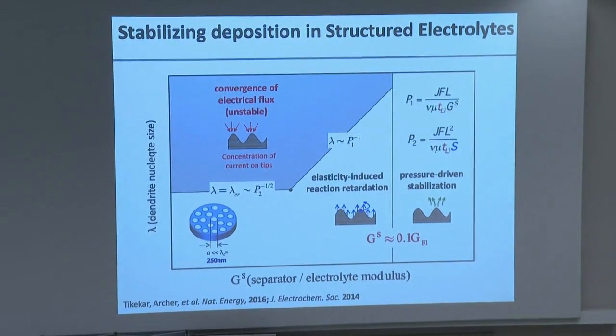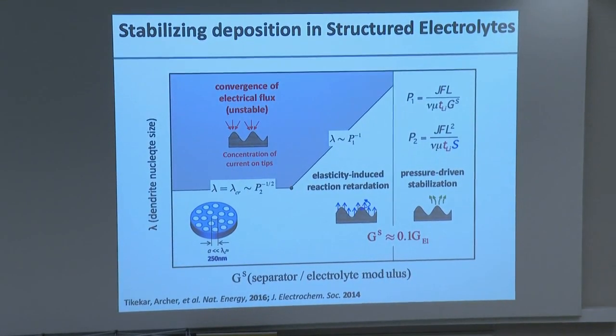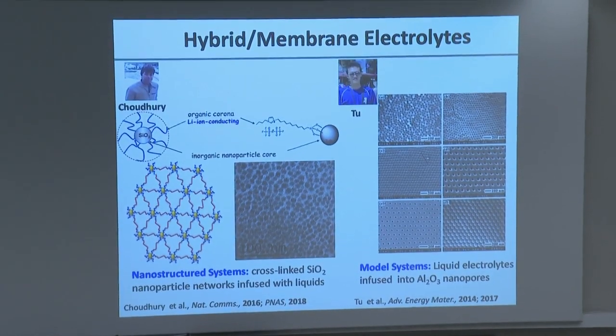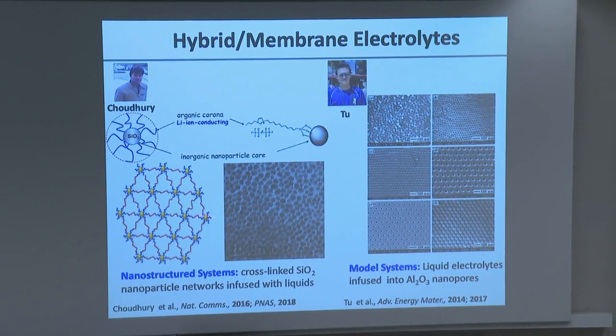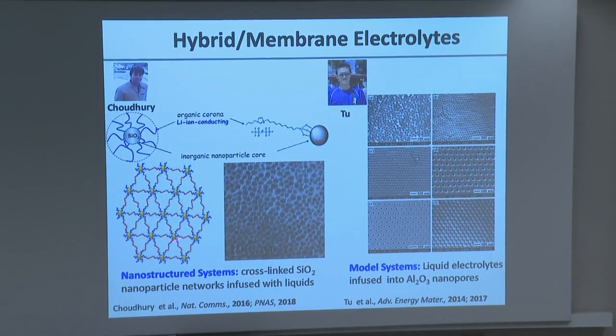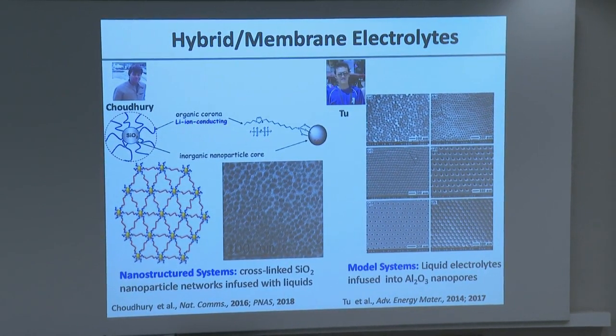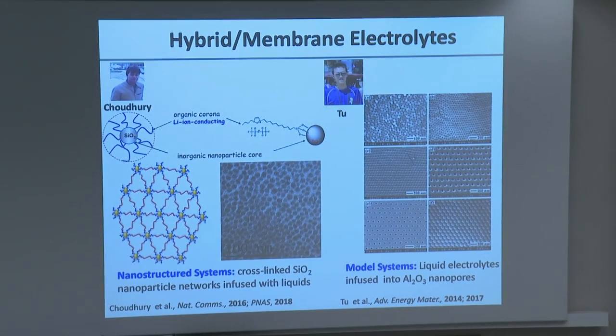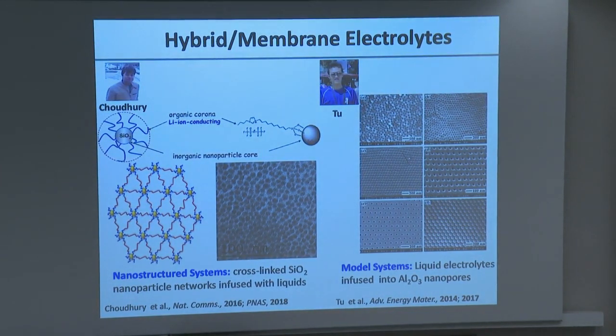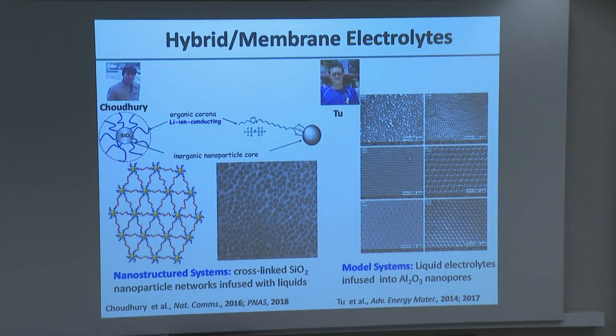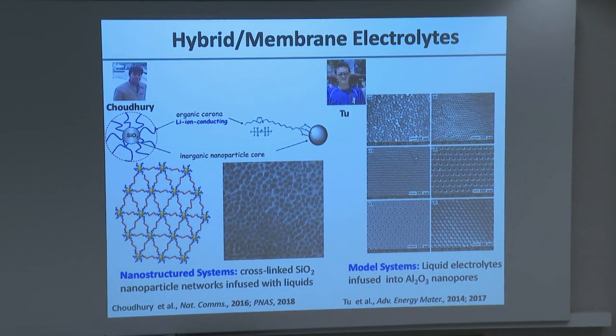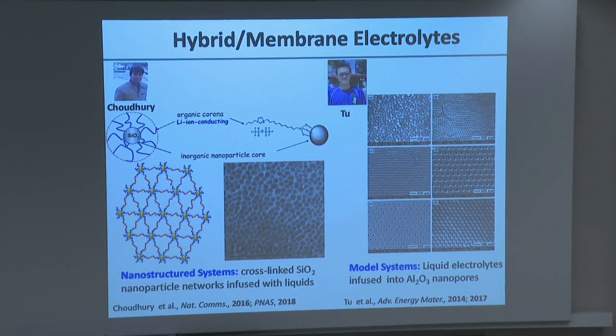The way we did it is to create what are called nanoporous electrolytes in two different configurations. One is electrolytes created by cross-linking nanoparticles. These are like porous media, where you control the pore size, that 250 nanometer number, by basically the length of the ligands that connect the particles. So that's relatively easy to do from chemistry.